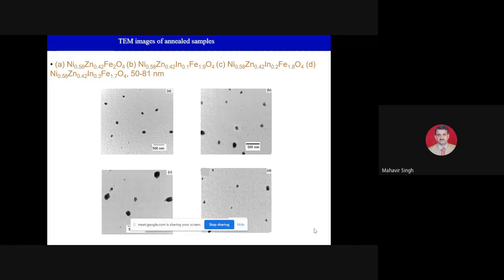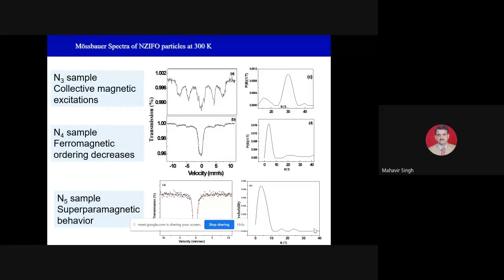If you need a high yield product, then I think you have to choose some other method. But if you want a low yield product, then this method is very, very useful, where we can use a surfactant. By adding the surfactant, we can control the shape, size and morphology, and we can easily achieve SPM also. So this is clearly superparamagnetic kind of behavior.